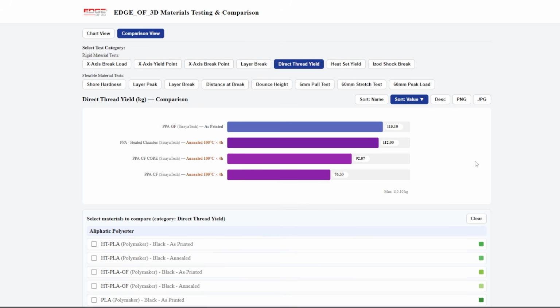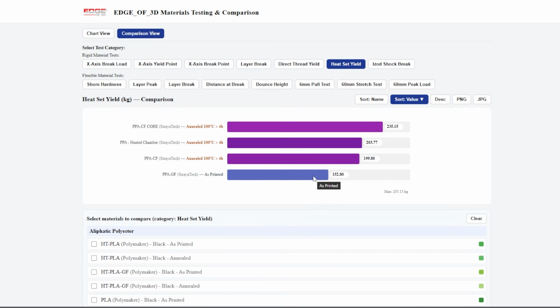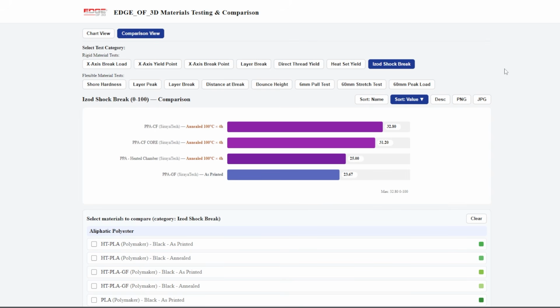Direct thread. PPA glass fiber did excellent on direct thread, 115.1 kilograms. That's a very respectable number. Heat set, just the opposite. It did the worst on the heat sets. It only added 132.80 kilograms of force on the heat set. Still very good numbers. And then the Izod shock test, and that's this one here with the PPAs is backwards from what everything else is. Normally, as you add fibers and stuff to the material, the Izod shock test numbers go down. But for whatever reason with PPA, it's the opposite. 23.67, which is still a good number.